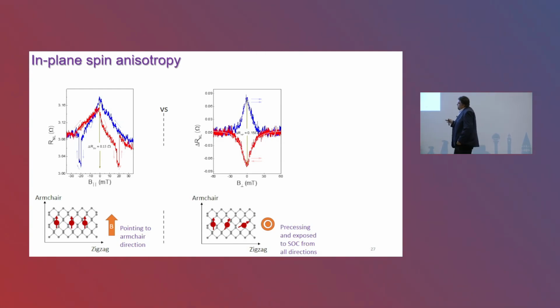Okay, so by now we know that the spins pointing out of plane live much longer than the in-plane ones. But the question is, does it matter if the spins are pointing along the armchair or zigzag direction? Indeed, it should, because the electronic mobilities are different, so the effective masses are different along the armchair and zigzag directions. So it's really also important whether the spins are pointing in plane or out of plane.